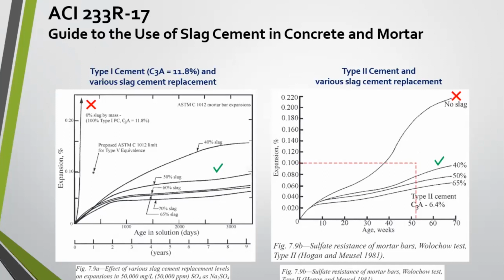On the right, we're looking at a type 2 cement, a moderate sulfate resistant cement. Then we have slag cement at 40, 50, and 65% substitutions. Again, you can see the dramatic difference when we get out to a year with the slag substitution and how that affects our permeability and sulfate resistance.